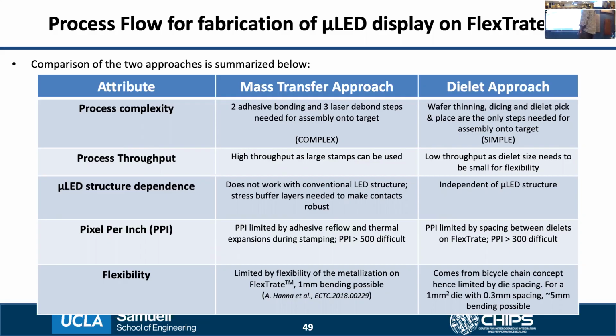Then finally, in terms of flexibility, the mass transfer approach, because the LEDs are essentially present on the surface of the PDMS, a very thin surface of the PDMS, the flexibility is really limited by the flexibility of the metallization itself, and up to 1 millimeter bending radius is possible. However, in the case of the dielet approach, because the flexibility comes from the bicycle chain concept, it is limited by the die spacing. So from ANSYS simulations, we found that for a 1 millimeter square dielet with 300 micron spacing, which is what we typically use, up to about 5 millimeter bending radius is possible without damaging the device.